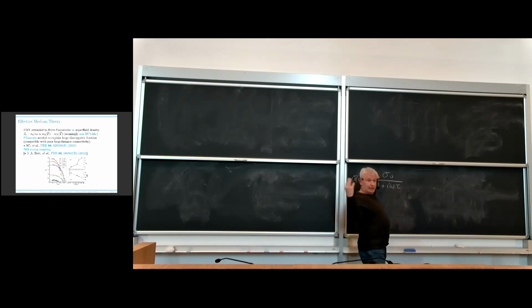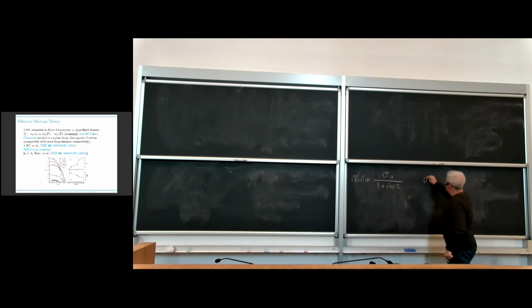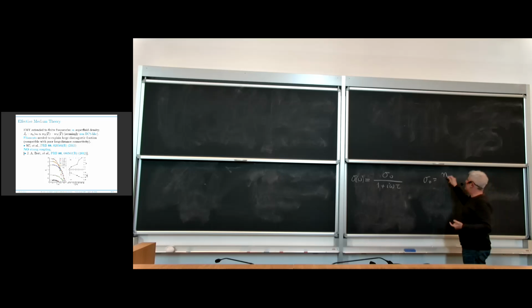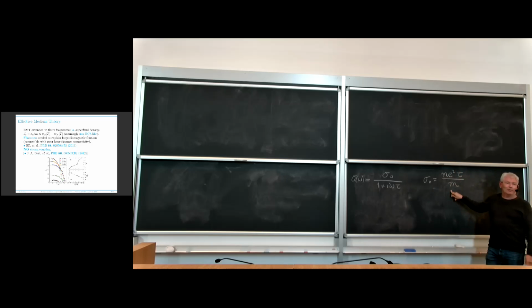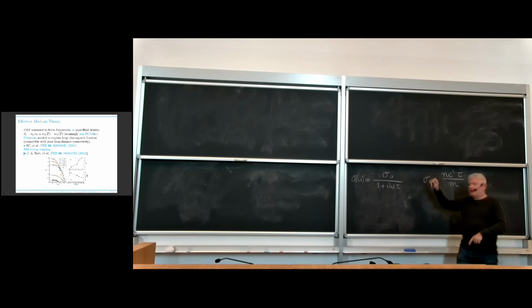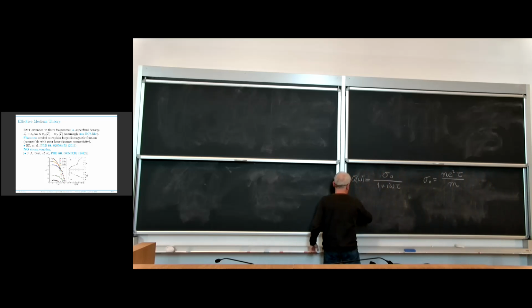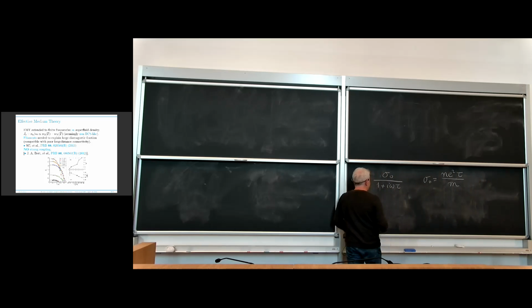What is sigma naught in the Drude model? In the Drude model, sigma naught is related to the density of carriers times their charge squared, times the scattering time divided by their mass, the mass of the carriers. This is the standard Drude model. Now, let me calculate the resistivity, which is the inverse.